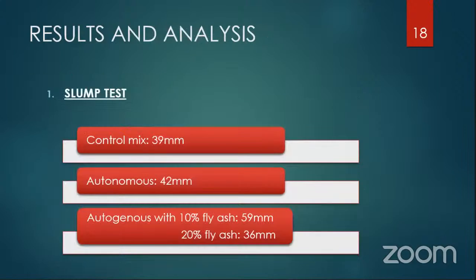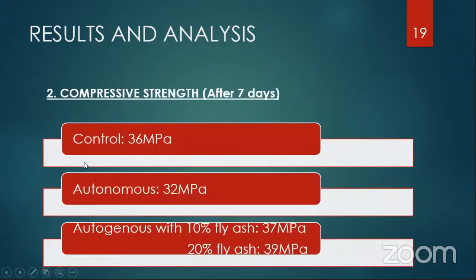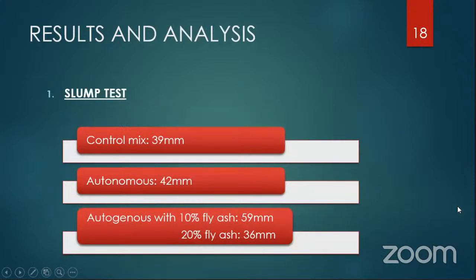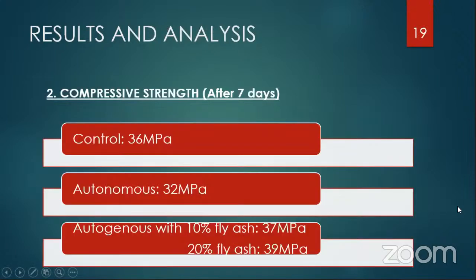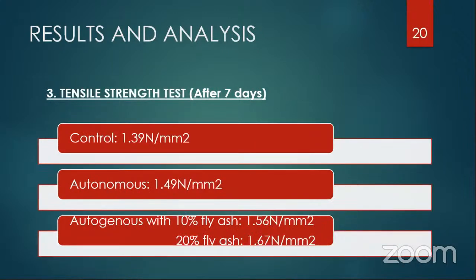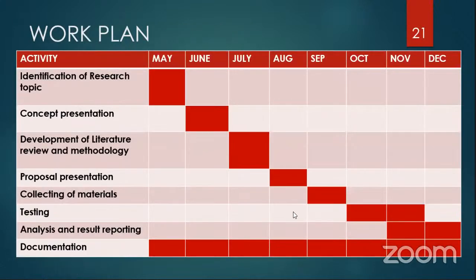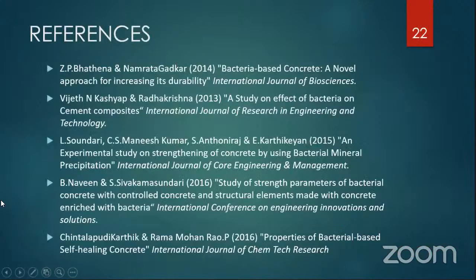These are our results for the slump test. We did it for the control, the autonomous and autogenous. After 7 days, we also did a compressive strength test for the cubes. The results are there: 36 for the control, 32 for the autonomous, and the 10% fly ash and 20% fly ash. For the cylinders, we also conducted the split tensile strength test after 7 days. These are the control, autonomous, and autogenous.